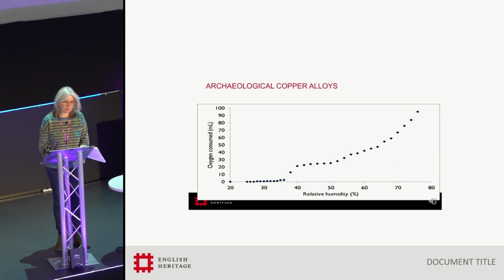On this graph, we can see the equivalent for copper alloy. This is Thickett's research, which also fits in with about 3 other people's research. RH, again, is the key factor in which cuprous chloride reacts to cause active corrosion. Different studies have produced different thresholds for the start of the reaction. Data from English Heritage and British Museum research shows that there is a risk above 35% relative humidity.